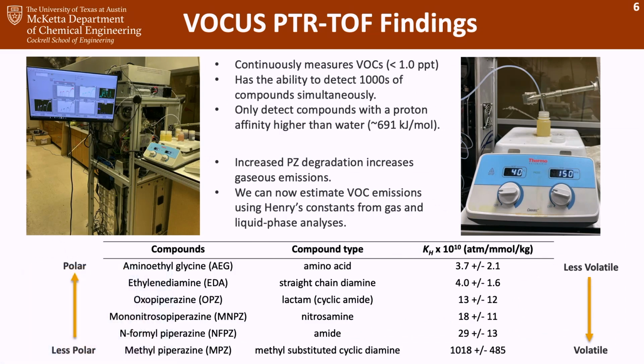So finally, with Dr. Pavel Mishtov, we were able to use his Vocus PTR-TOF, and this instrument's able to continuously monitor volatile organic compounds down to about 1 part per trillion. This technology has the ability to detect thousands of compounds simultaneously, and this is all done in the gas phase. So using this instrument, we're then able to relate what we had already known, which is as time goes on in the process, piperazine begins to degrade heavier. And so we know in the liquid phase degradation products go up, and now we can confirm in the gas phase that our degradation products go up.